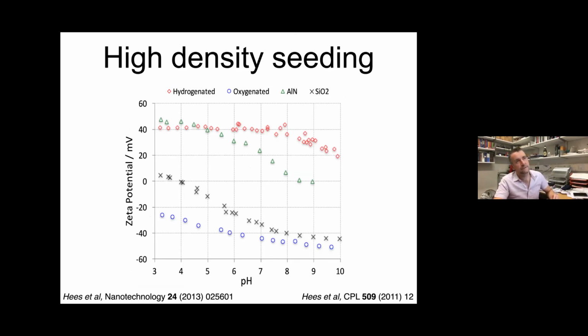Years ago, when we went to the St. Petersburg conference, the seeding was working really badly, right? So for the non-growers, what we're trying to do is take a silicon surface and just coat it with as many diamond particles as possible, right? But you don't want two layers, you want a monolayer, right? And you want it as thin as possible and in size as uniform as possible.